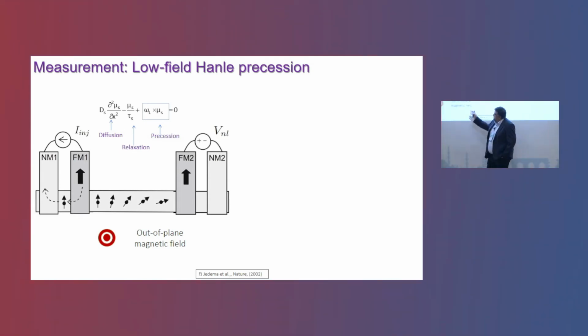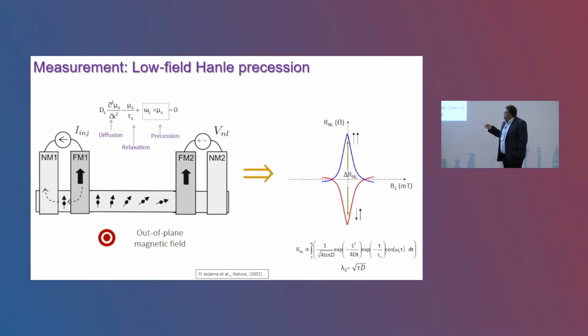You again do the same measurement, but now the spins point in plane, and then you start to apply a very low magnetic field. The spins start to precess within the plane, and depending on the direction of the spin with respect to the detector electrode polarization, you get these kinds of Hanle spin precession curves. By doing some fitting, you can get an idea about the spin lifetime, the spin relaxation time, and also the spin diffusion constant, which gives a parameter called the spin relaxation length.